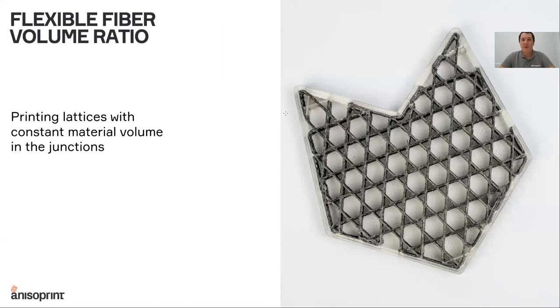That was the second one, and the third one, which I think is one of the most important for us, is the capability of printing lattices. I will talk a little bit more about lattices later during this webinar, but it's important to note here that lattices cannot be printed with any other composite fiber printing approach because of the junctions. Lattices consist of unidirectional ribs that have intersections, junctions where fibers have to intersect, and they cannot be cut, stopped, and restarted at the intersection point.